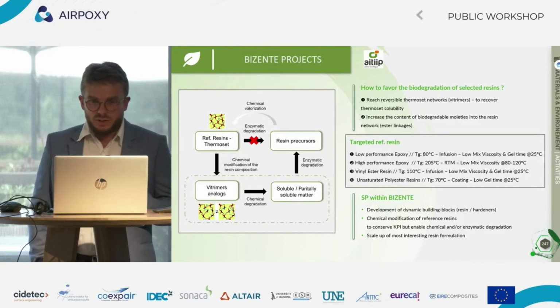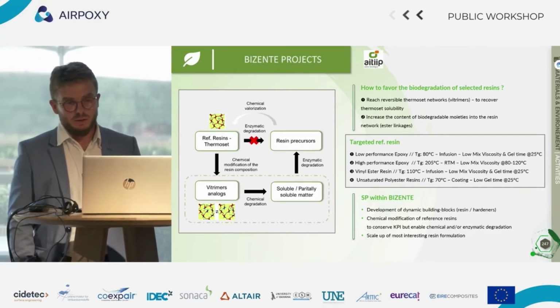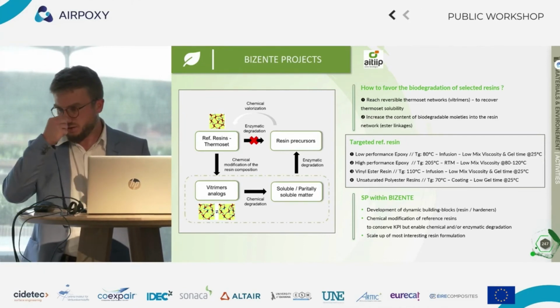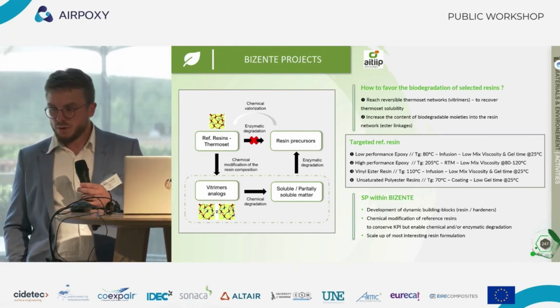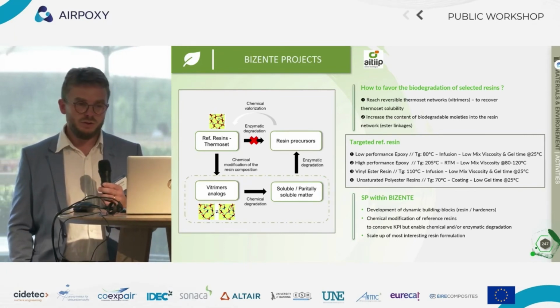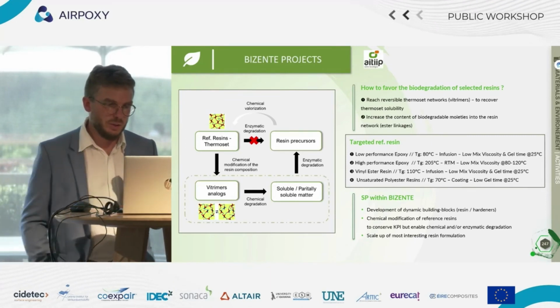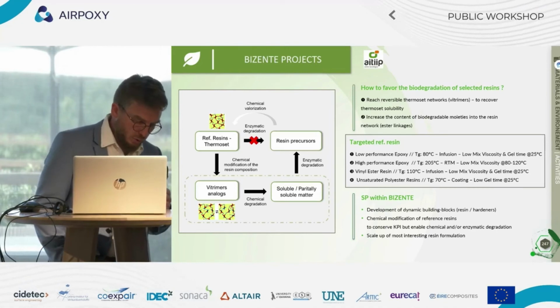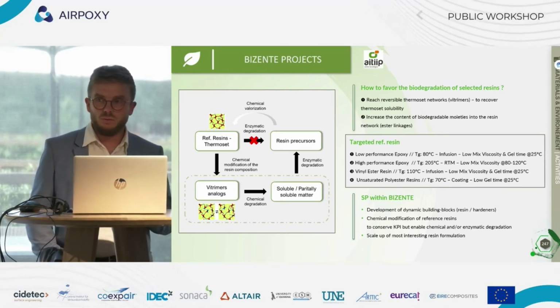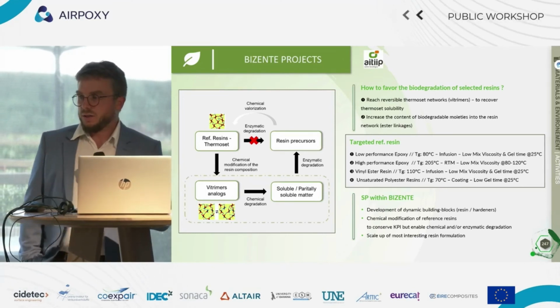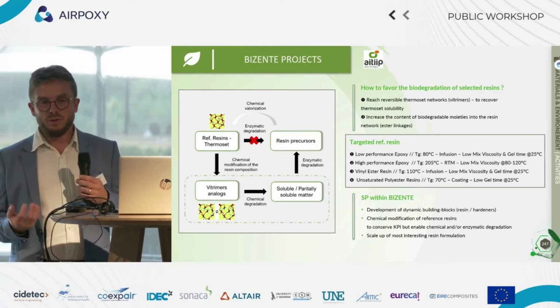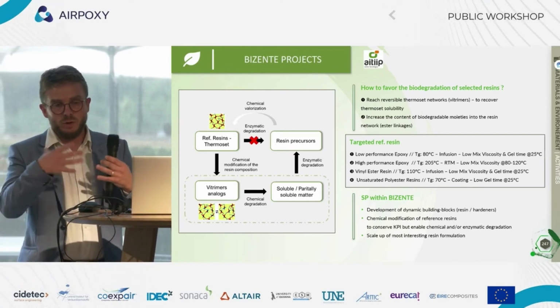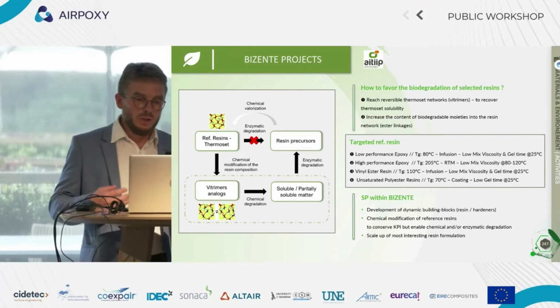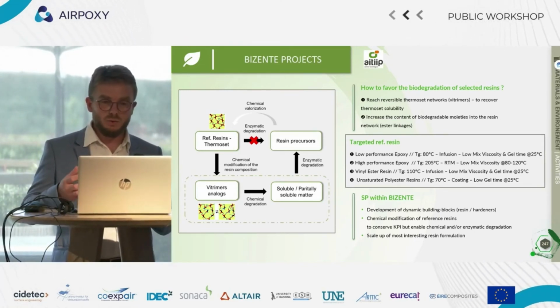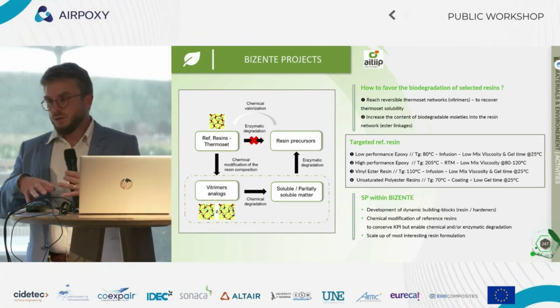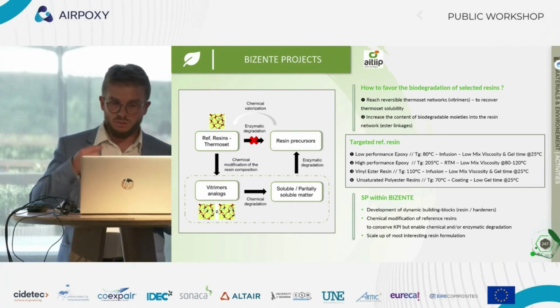A word about Bizente project that is ongoing. So it's still based on the Vitrimer approach, but in this case, the idea is to put chemistry into the materials that will help its degradation, but also help an enzymatic degradation step. So the starting point was if you put a thermoset material to an enzymatic degradation process. In this case, because the accessibility into the polymeric network is impossible for the enzymes, they will only act at the surface and the degradation will not occur properly. So the idea was to somehow have some reversible bonds to be broken by a chemical degradation process to somehow open a bit the materials and give access to the enzymes.